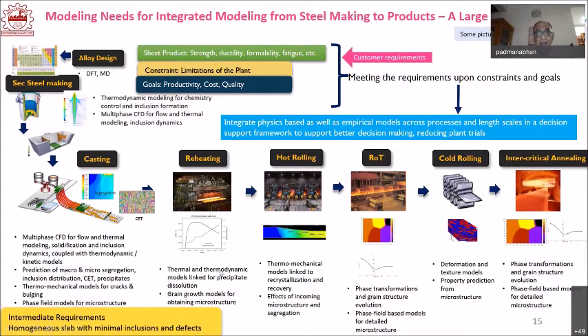And if you go to reheating, mainly, the temperature has to change, and therefore you require a precipitate dissolution model and grain growth. In hot rolling, there is also shape change of the grains, recrystallization and recovery, and incoming microstructure can be different from heat to heat, and also segregation could be a problem. In runout table, temperature goes down, cooling is done, and therefore austenite transforms to ferrite, and this will lead to phase change and also microstructure evolution. Phase field methods are very handy here. And then cold rolling can be analyzed in different ways. Deformation, of course, is there. In addition to that, texture models.